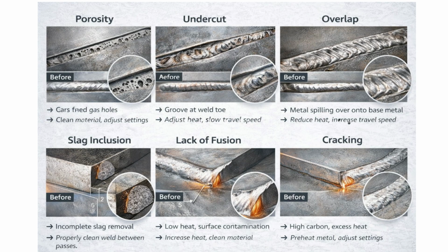Undercut is a groove melted into the base metal at the toe of the weld. It's caused by excessive amperage, improper electrode angle, or too fast travel speed. Reduce your amperage, adjust your work angle, and slow down slightly. Overlap or cold lap occurs when the weld metal rolls over the base metal surface without fusion. This indicates excessive heat. Reduce amperage, increase travel speed, or improve your technique.